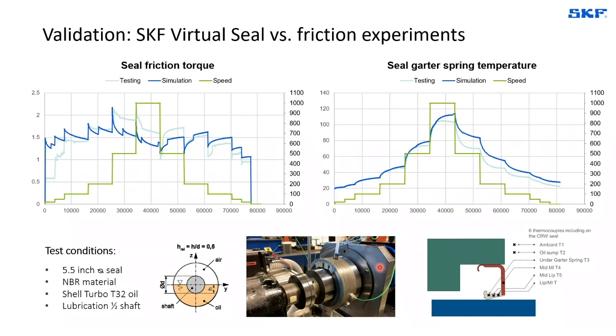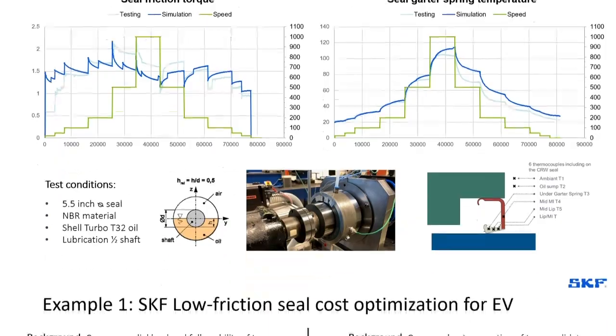Similarly, we placed different thermocouples around the seal to understand the temperature distribution, and I'm showing here an example around the garter spring area, so in this location. And you can see, again with the same scale in dark blue, what the response of the model is versus the actual test data. And I think we can agree that in this case, but also in the others that I'm not able to show today, we are in quite good agreement with the actual experiment results.